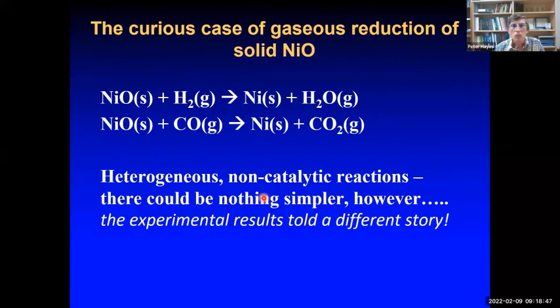Now, I want to take you to a case of reduction of nickel oxide. Nickel is in the news at the moment because we're talking about use of nickel in lithium-ion batteries, for example. So this is an example then of how we can make nickel metal from nickel oxide, again using hydrogen and CO, a very simple example. So what do we know about this system? It's heterogeneous, that is, involves a phase boundary, in this case a solid and a gas, and creating a new solid product. It's non-catalytic, so this is not a catalytic reaction, it's a phase transformation or chemical reaction. They couldn't be much simpler than this sort of reaction.